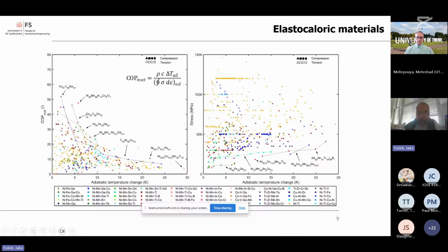Okay, if we take a look at these plots, we can see that by far the most studied are nickel titanium alloys, which are marked in orange here, both in tension and compression. Well, they are not optimum, neither from the efficiency nor from the stress point of view. Based on the literature review, we can see that the most optimal seems to be magnetic shape memory alloys, such as nickel iron gallium or nickel manganese based, or even some nickel titanium doped with copper or iron. But this is purely from the COP point of view,